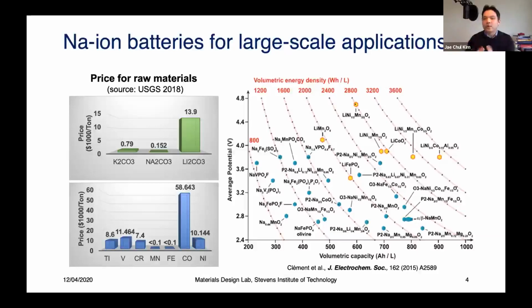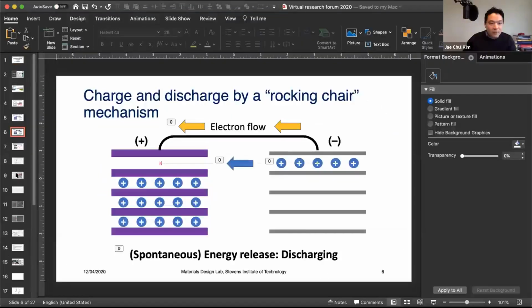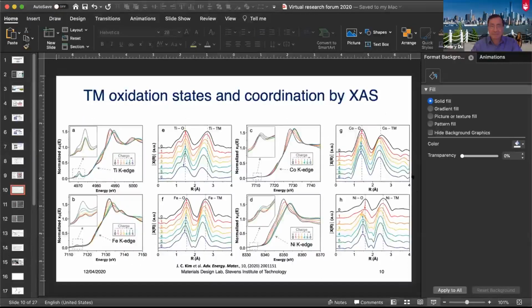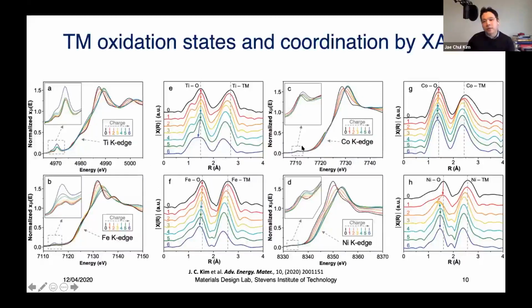Our ultimate goal is to utilize manganese and iron. But at this moment, cobalt does help. If you see the XANES curve in this plot, in the small box, this shows the octahedral symmetry of the transition metal. Unlike others, say for example titanium, iron, and nickel, the cobalt pre-edge is pretty stable, meaning that it does not change its symmetry upon charge and discharge, upon oxidation. This means cobalt actually stabilizes the material structure. So without cobalt, you're going to lose some reversibility.